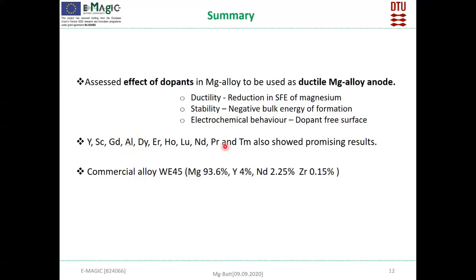Based on these identified elements, we also see a commercial alloy which is already available. This is the WE45 alloy, which contains yttrium, neodymium and zirconium. So these elements are shown to be promising. The only element not in our list is zirconium. Zirconium was not in our list because it is not soluble in magnesium. But several studies indicate that zirconium is soluble when it's added with the rare earths. So we definitely recommend this commercial alloy, which can be tested to be used as a ductile Mg alloy anode.